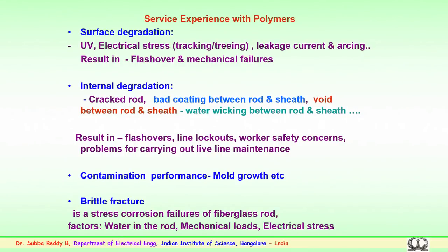Similarly, electrical stress: because the insulators are continuously under electrical stress, they are prone to tracking and treeing. In case the surface becomes hard, stiff and brittle in nature over a period of time, the hydrophobicity property which we were discussing could be reduced because of the continuous hardening of the silicone rubber, and this leads to higher leakage currents leading to arcing.